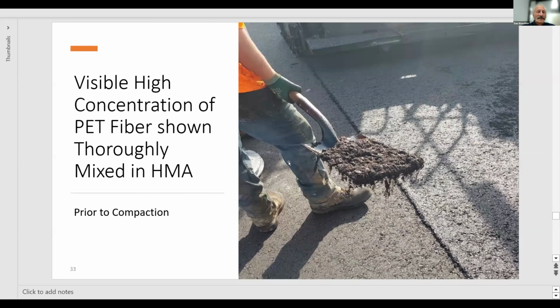You can visibly see the high concentration of the PET fiber thoroughly mixed in the hot mix asphalt. Those strands hanging down from the shovel, those are the PET fibers that we hope will give us the tensile strength and the resistance to cracking that we're looking for.